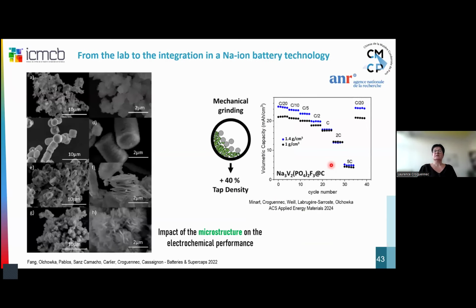And we have also shown that by playing with the synthesis, we can really play with the microstructure of these materials, moving from nanospheres here to platelets and to sand roses here. And depending on the microstructure, we can also play on the electrochemical performance. And we have shown very recently that by mechanical grinding, we can really increase the tap density of this material, while maintaining performance in that case.